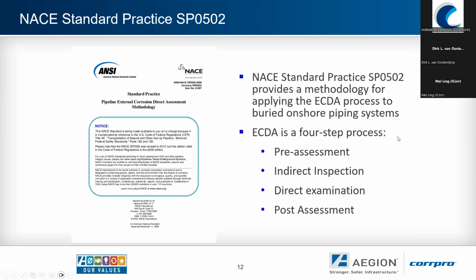I think the important part here is we did it in phases so that there are 4 steps. The pre-assessment step is important and often the most underestimated as far as importance and also effort required. The pre-assessment step is designed to review available information and knowledge with regards to a pipeline system, and determine at that point whether or not external direct assessment as a process is applicable, if there's sufficient information to justify it. And also at that point, in the pre-assessment, determine which tools will be acceptable based on the condition of the pipeline, based on physical parameters and topography.